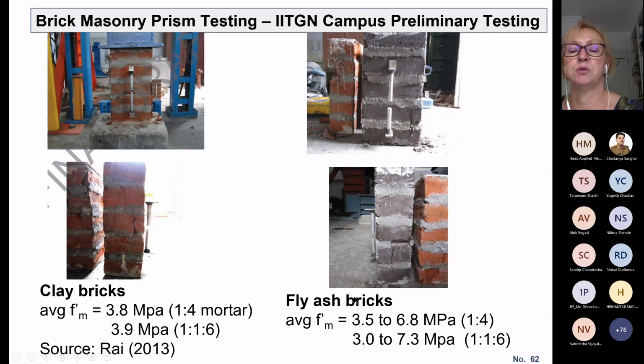Whereas for fly ash bricks, the strength F'(M) was in the range of 3.5 to 6.8 megapascals for 1/4 mortars, so the same mortars. So maximum values were 6.8 and 7.3, which are significantly higher than 3.8 or 3.9. Based on that and other, more extensive testing, it was possible to decide to use fly ash bricks for this.